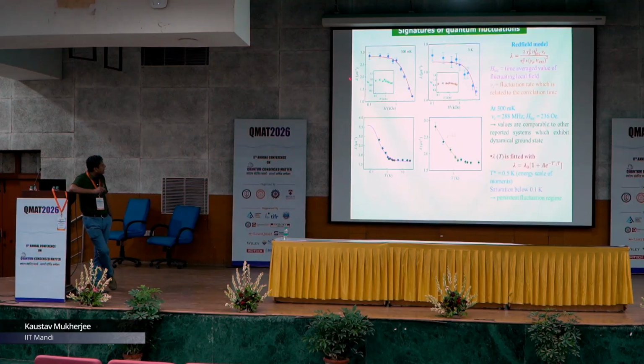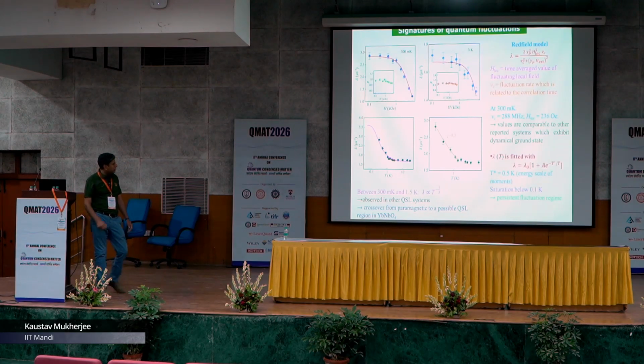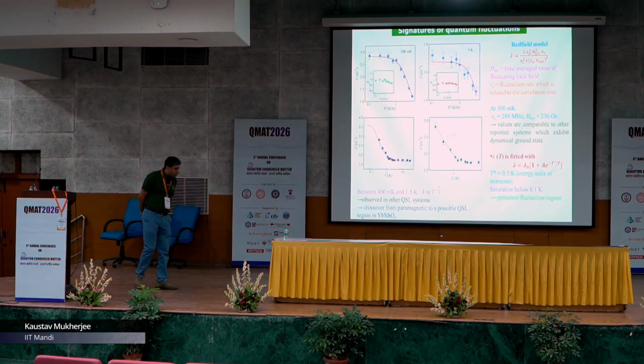We fitted this relaxation rate with the Redfield model and found the fluctuation rate to be around 228 megahertz, which is comparable to other reported systems having a dynamical ground state. Also, lambda versus T is fitted with a phenomenological model, and we found that it saturates down to 0, where we found a persistent fluctuating regime below 100 millikelvin. Also, the relaxation rate was found to vary as T to the power 1/3 between 300 millikelvin and 1.5 Kelvin, and such variation is observed in other quantum spin liquid systems. So, it implies that in YbNbO4 there is a crossover from a paramagnetic to a possible quantum spin liquid regime.